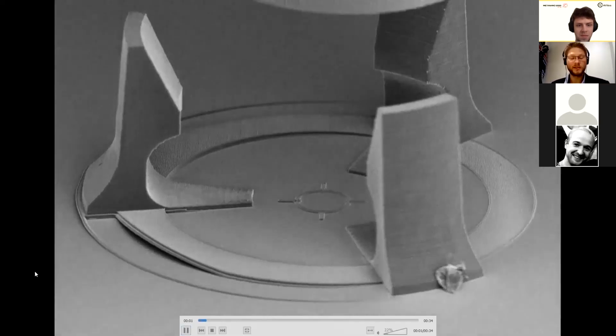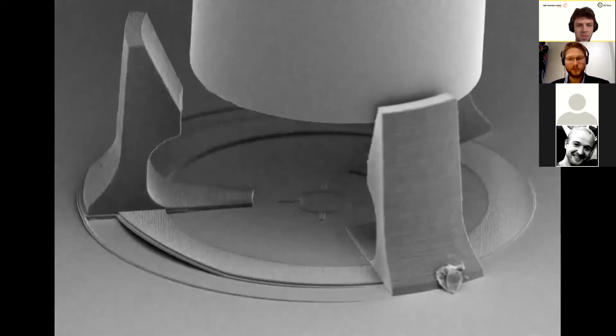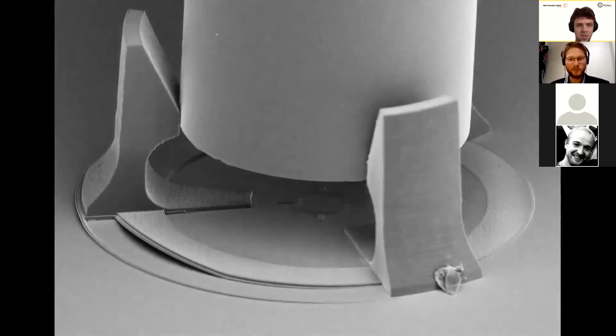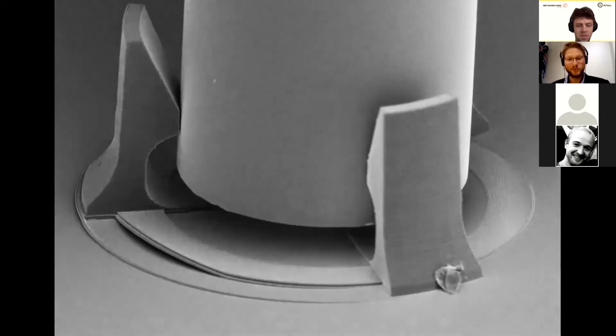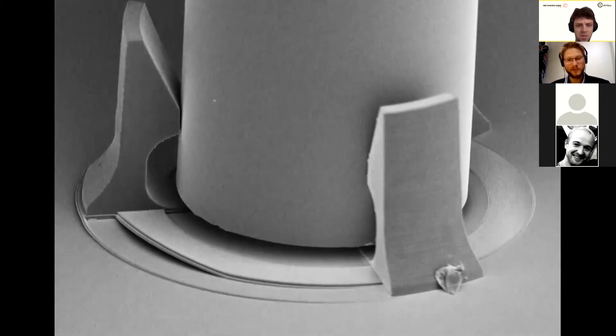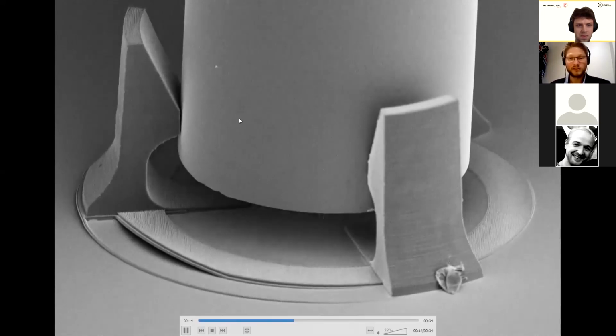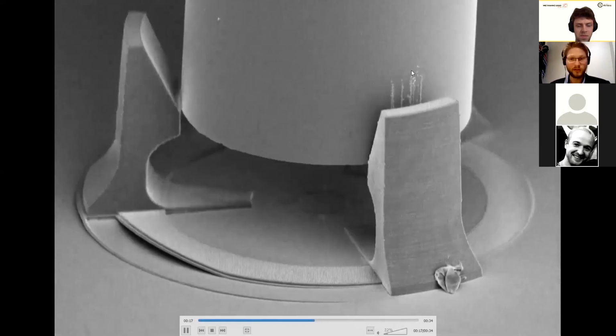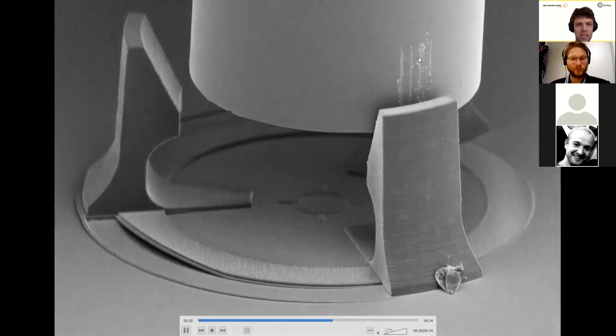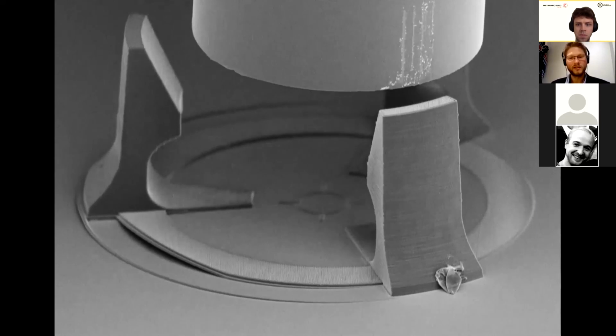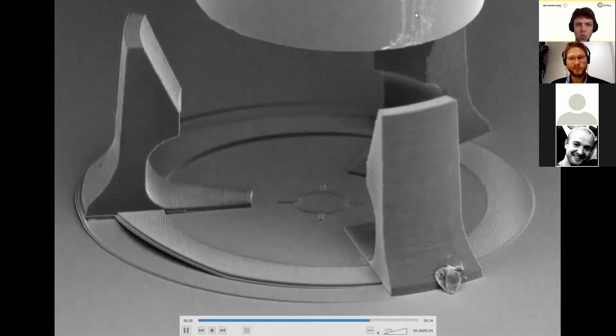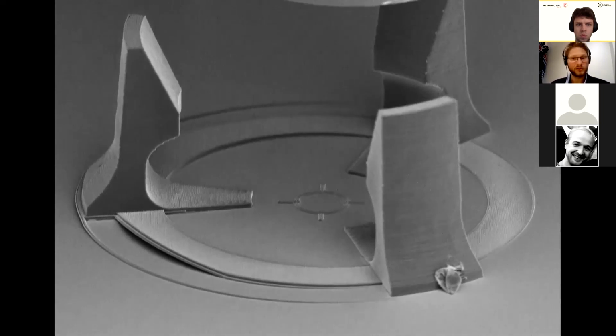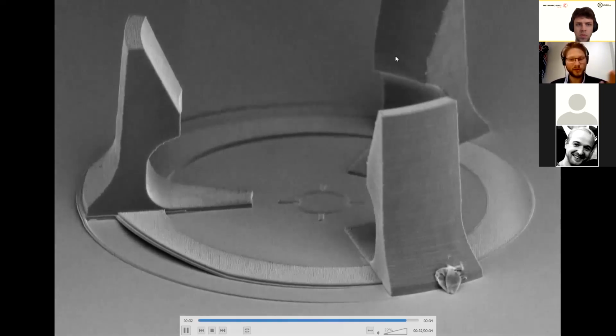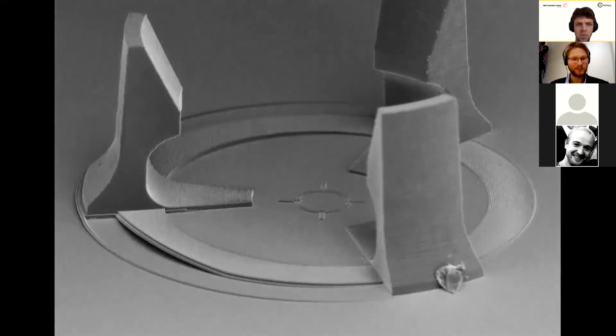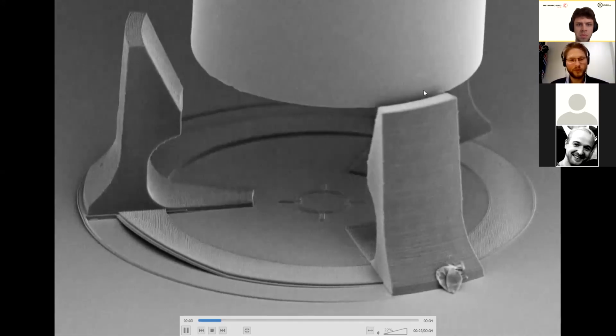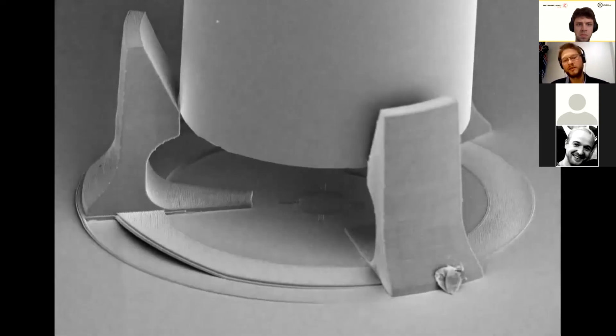And this is the consecutive animation made of photos from a scanning electron microscope, about 800 of them, when we are putting the optical microfiber into our microport. This optical fiber is covered with gold. As you can see on the right side, there are scratches. So we just scratched the gold, but also, as you can see, the structures are not only straight, but a little bit curved, which proves that this spring-like action works. So indeed, it was redirected towards the center of this structure.